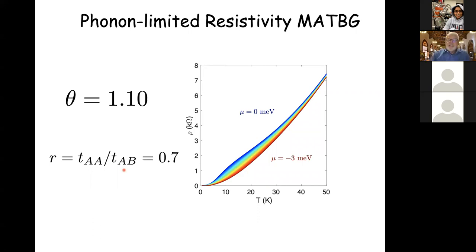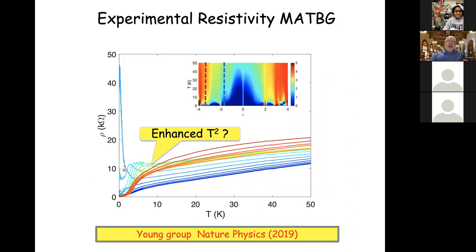mainly actually because of interaction effects. But this kind of picture is qualitatively right. This is what resistivity you would expect in this system, using the well-known electron-phonon interactions of graphene. But if you compare that with experiment, then you will see that, first of all, the resistance at low temperatures is much, much larger than you would expect based on the graphene